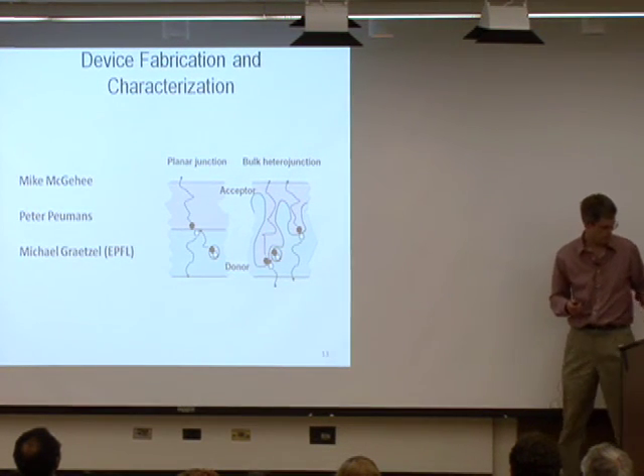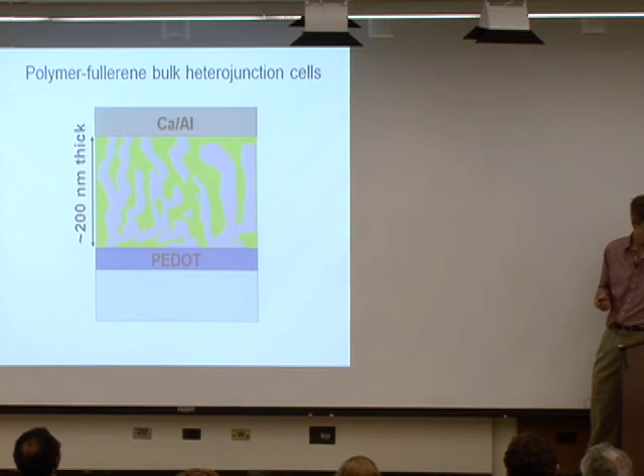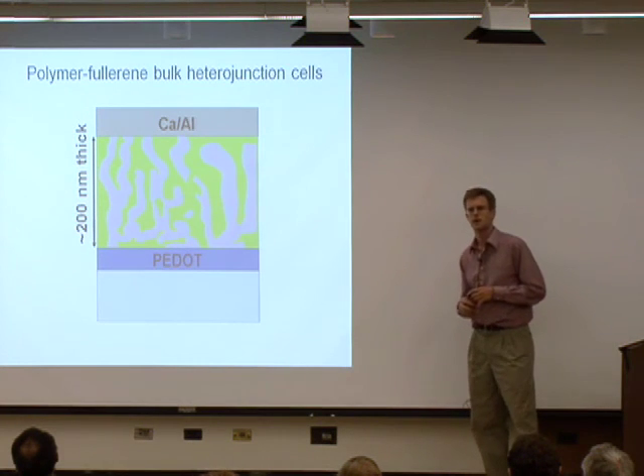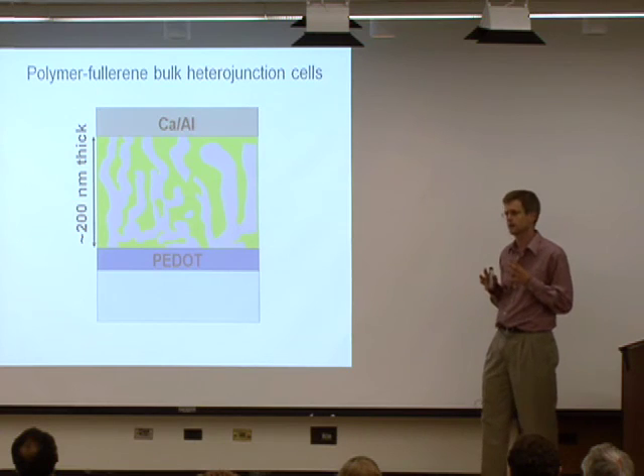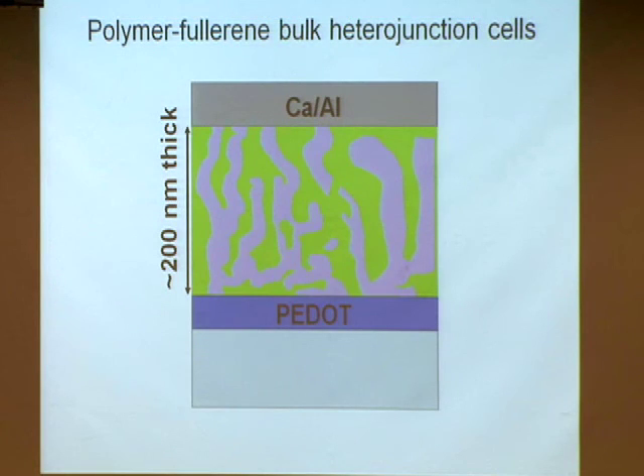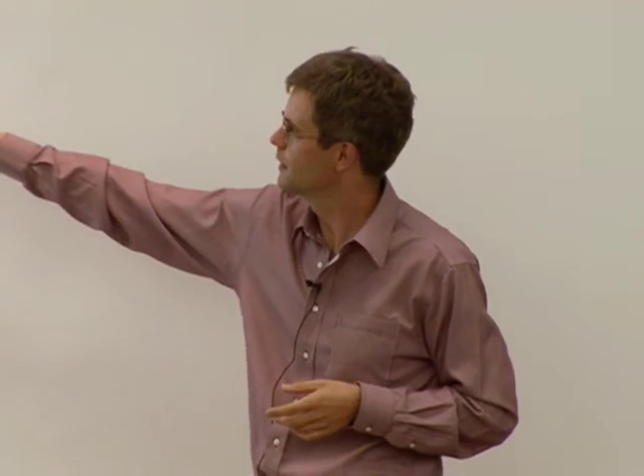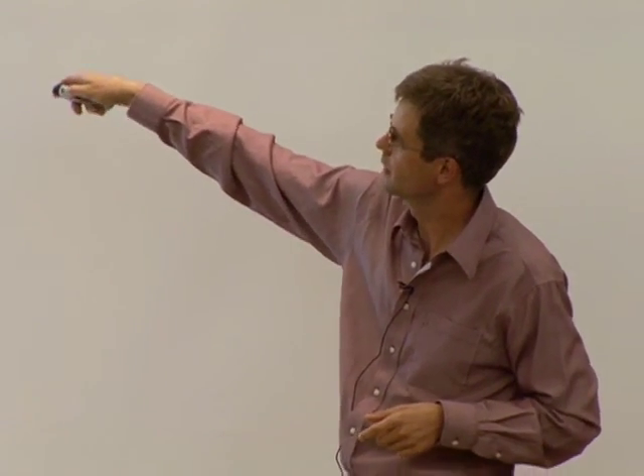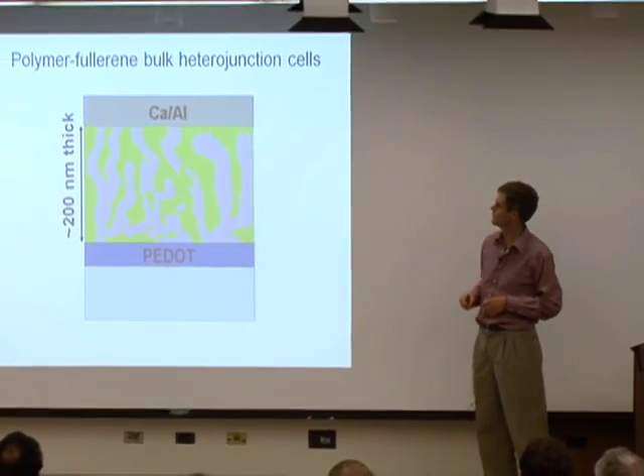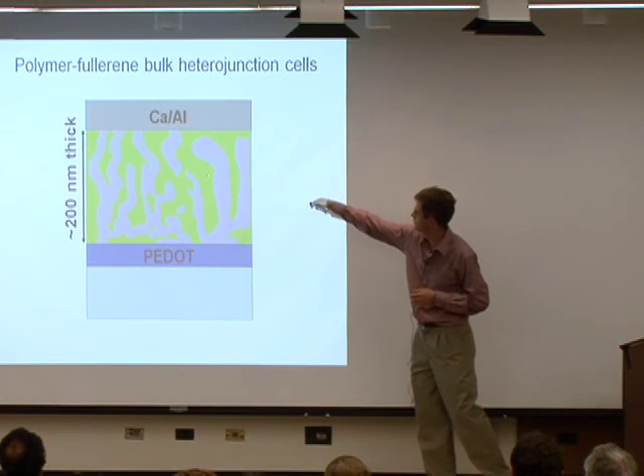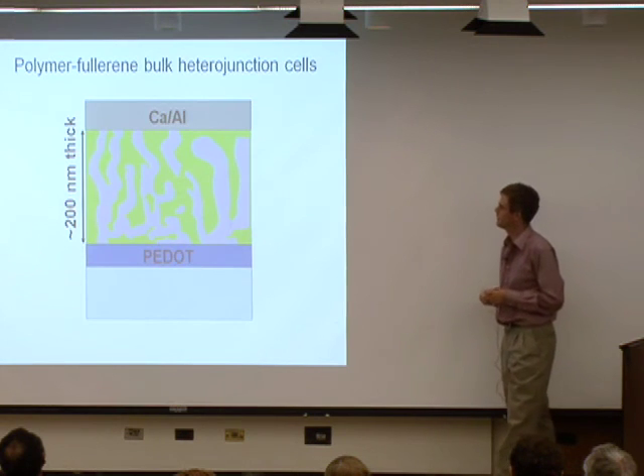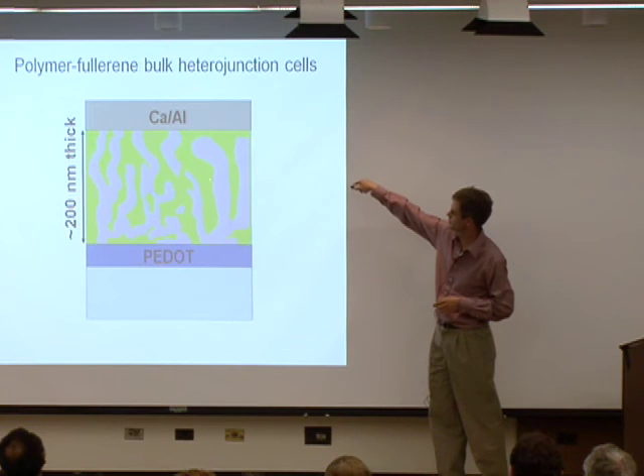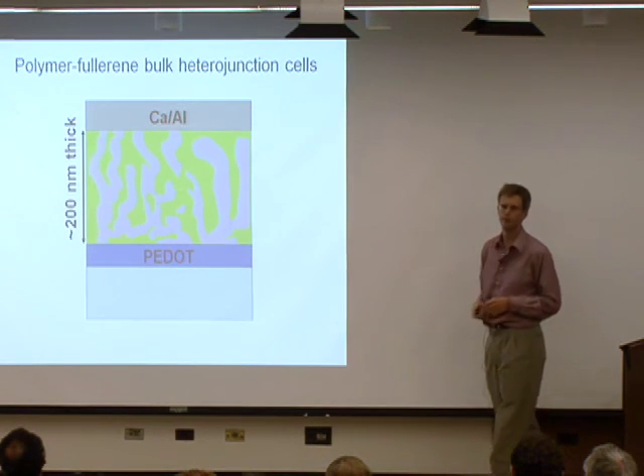So one of the keys to making these cells work well is that you have to pattern the 2 semiconductors right at the nanometer length scale. So here you see an example that can be made by blending a semiconducting polymer. Those are long chain-like molecules with fullerenes, which are little balls of carbon that look like a soccer ball. When you dissolve them together and cast a film, you can get a structure that looks schematically like the one you see here. And then no matter where light is absorbed, the exciton is going to be near the interface, and therefore you can split up the excitons. And then the challenge becomes having an architecture that allows the electrons to have a pathway to one electrode and the holes to have a pathway to the other.